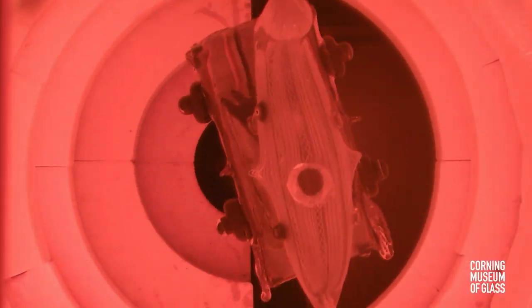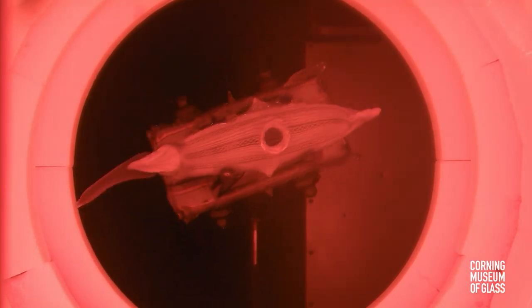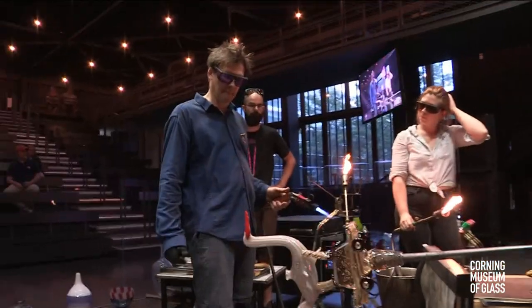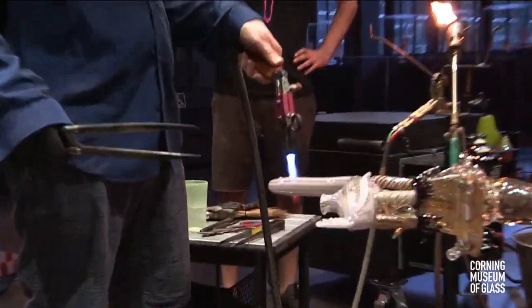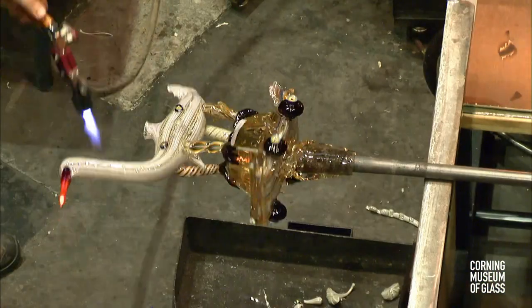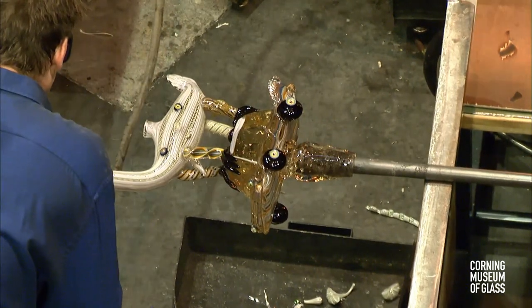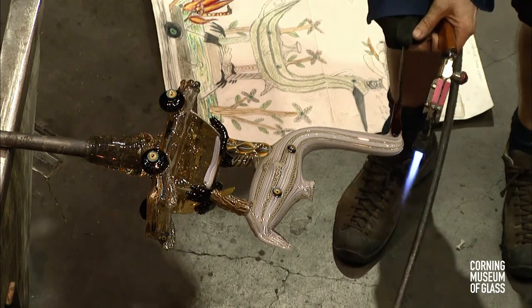But to order clear glass, you're looking at a few dollars a pound, depending on the glass. But when you start looking at the colored glass, you're looking at metallic oxides and compounds. So if I'm looking at green glass, that's iron added into it. So that's fairly inexpensive, but that's, I would say, in a range of $20 to $30 a kilo for kind of lower in green. And then you look at the pink glass. Pink glass uses gold chloride, so those are getting up to like $70 a kilo for the pink glass.